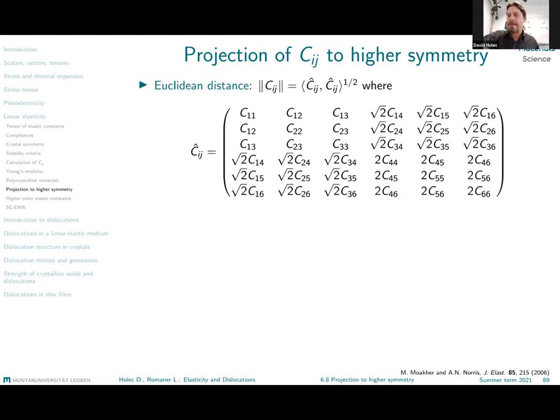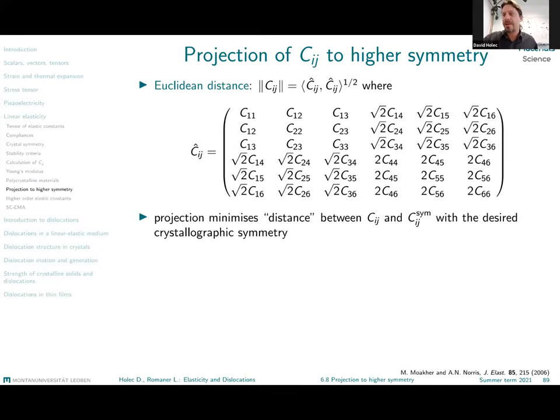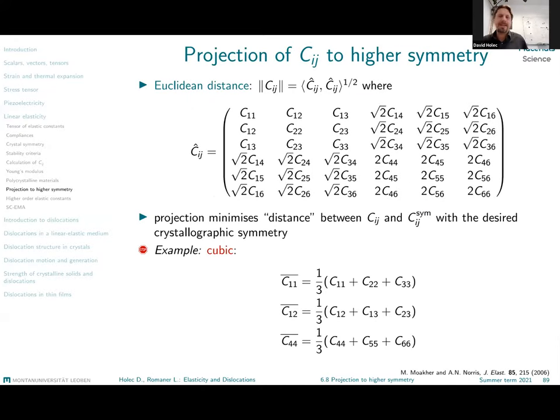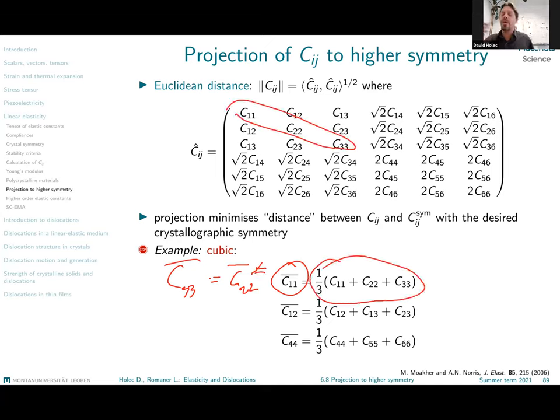And these projections, we have here now, for example, the expressions that come for the cubic material. Here it is trivial and it gives you a simple and false impression that to get the C11 value, which should be the same as C22, which should be the same as C33, of course, because of the cubic symmetry, you simply average the values that you get in your non-cubic symmetric matrix of elastic constants. Well, it works this nicely for cubic materials. It doesn't work this simply for other symmetries.